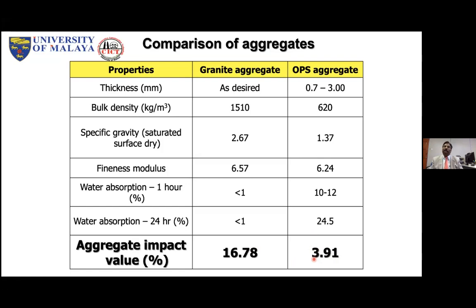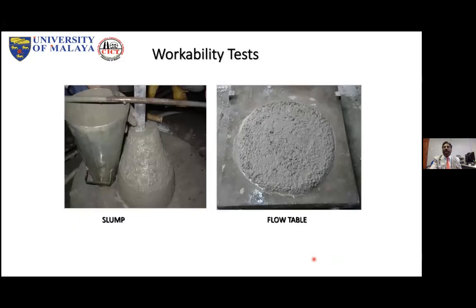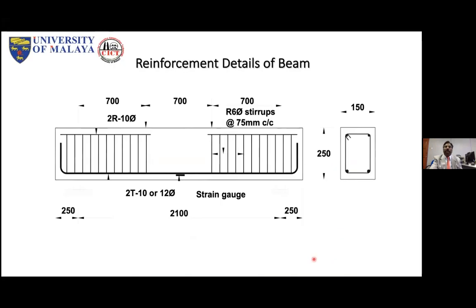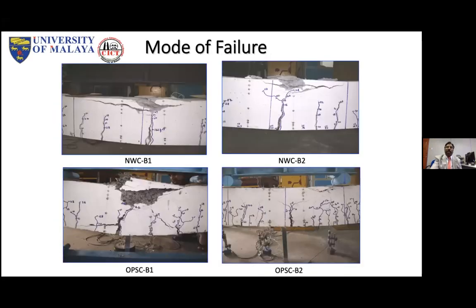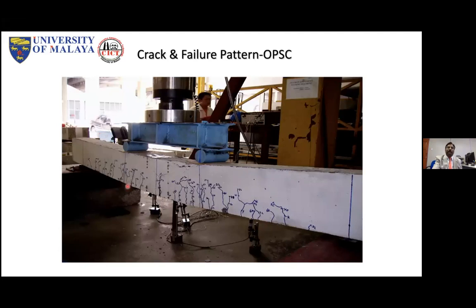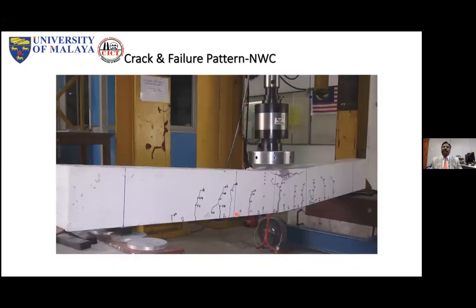There are different codes, and you need to understand which code you follow, though the procedure is the same. When you measure the aggregate impact value, this does not crumble. The shell can absorb the impact, number one. This is what enabled us to go ahead. Next, if you make the concrete and look at the deflection and deformation, the number of cracks in the shell concrete is double the number of cracks in the normal weight concrete beam.